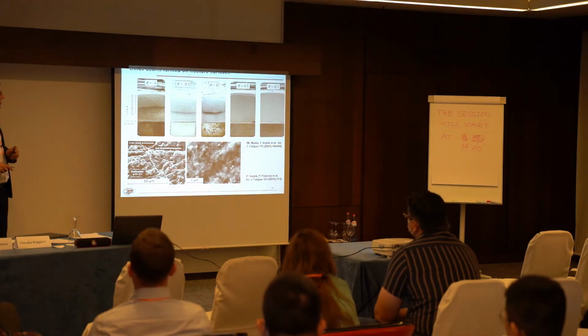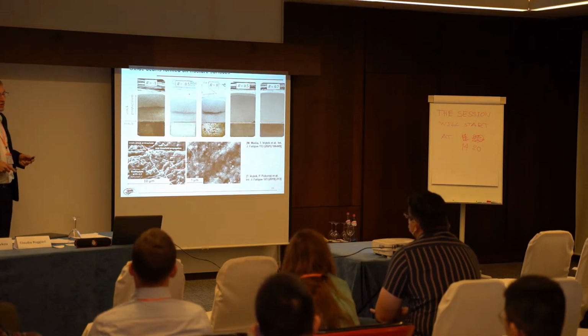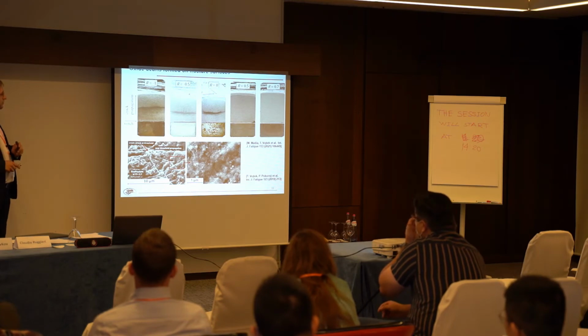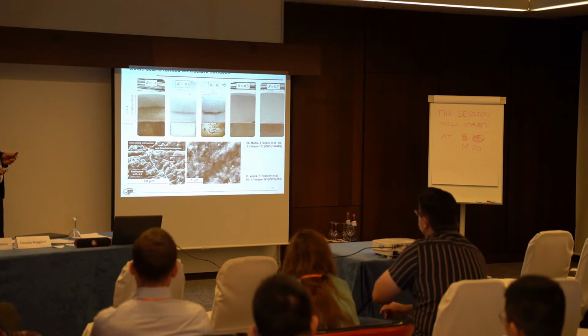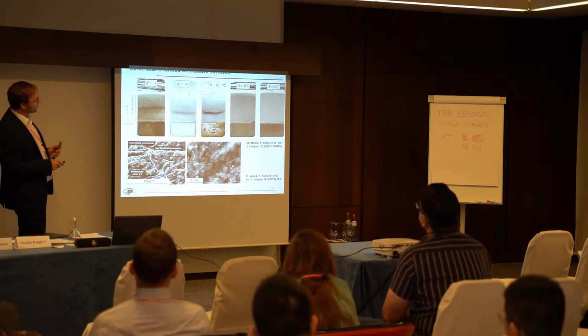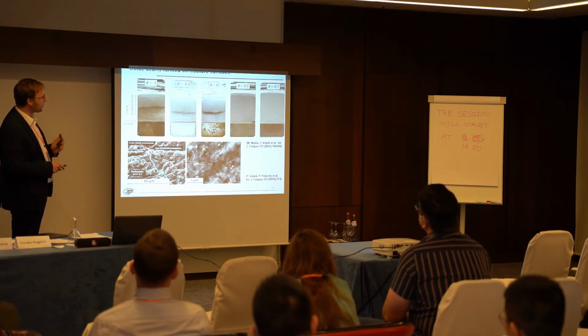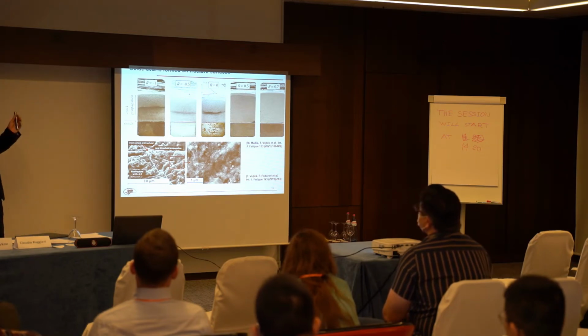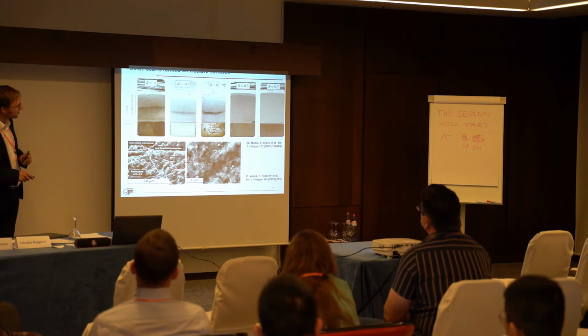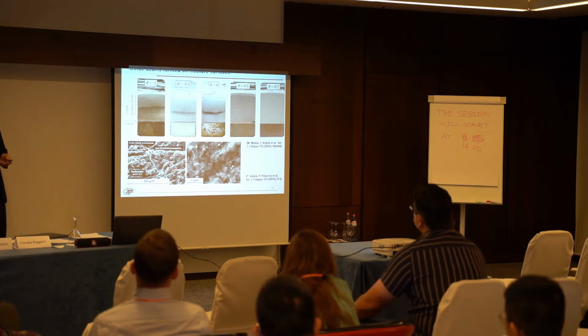Here is what we mean when we talk about oxide-induced crack closure. Here this very dark brown marks the fracture surfaces that originated in the near threshold regime, so there was a load decrease, and close to this line was the crack arrest at threshold. And as you can see, at large load ratios of 0.5 and 0.7, crack closure was limited because the crack was open, and we don't see anymore these marks of oxide. And then we can have a look at the fracture surfaces, and we can see this kind of typical structure for oxide particles.